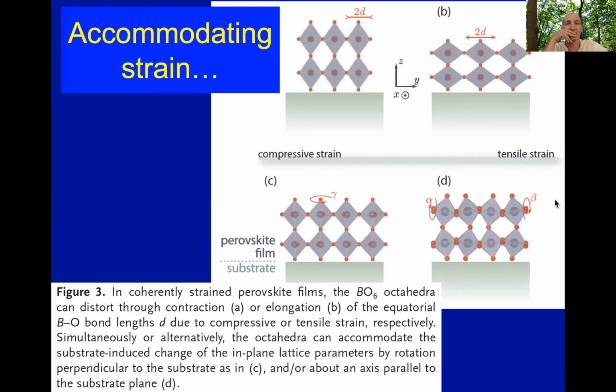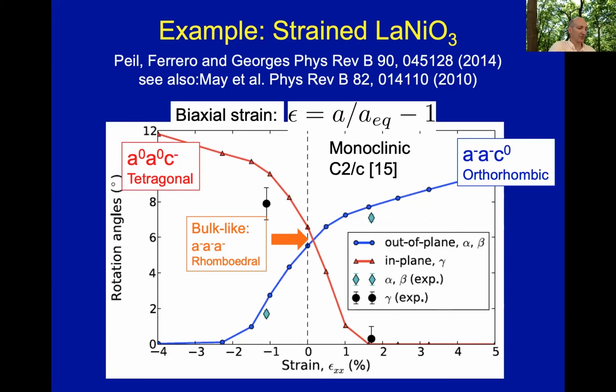When you grow the material under tensile strain, the opposite happens. You typically undo the rotations, so you get straighter bond angles in plane. But then the system buckles and leads to alpha and beta rotations. This is an example of density functional theory calculations coming to the rescue, where what you see here is a calculation in one of these nickelates, lanthanum nickel O3, under a given strain. To the left is compressive strain, expressed in percentage with respect to equilibrium, so negative means compressive strain. And to the right is tensile strain.